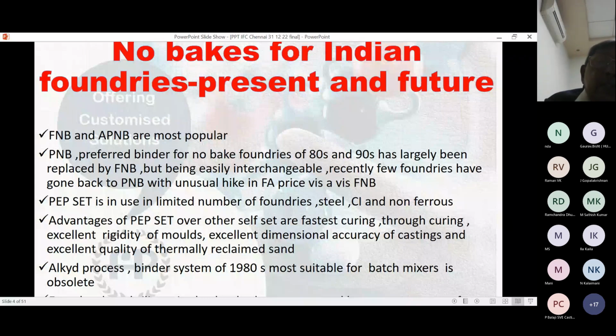The largest weight mold in India is made with PEP set, with the half mold being 2.5 tons of sand. So this type of mold you cannot expect from other types of binders. Furan is next, but Alphaset you cannot go for because it does not have that much dry strength to handle some bigger molds. And I talked about the mold that is in the loop line, that is a flashless mold. Alkyd process binder of the 80s, most suitable for batch mixer, is obsolete now.